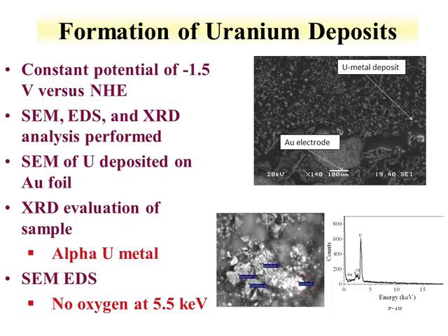This uranium-3 TFSI was added to the ionic liquid. Negative potential was applied. The metal deposition on the gold electrode surface was then evaluated by SEM, EDS, and XRD.